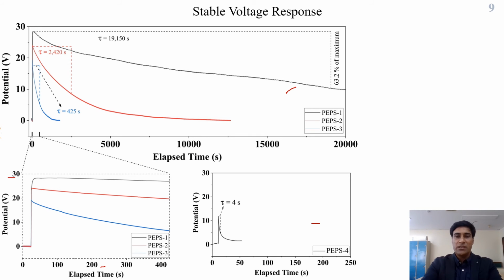So this is the stable voltage response when we applied a pressure of 2 kilopascal. Here you can see three lines: piezoelectric pressure sensor 1, 2, and 3, like PEPS1, PEPS2, and PEPS3. PEPS1 has high resistivity because of more Mg incorporation, so the longer decay time constant is 19,000. It is because of the high resistivity of the p-GaN shell. The piezoelectric pressure sensor with low resistivity exhibited a low decay time constant. In the case of pristine nanowires, the decay time constant is only 4 seconds, which shows significant leakage current.